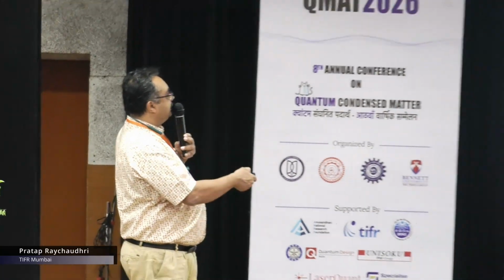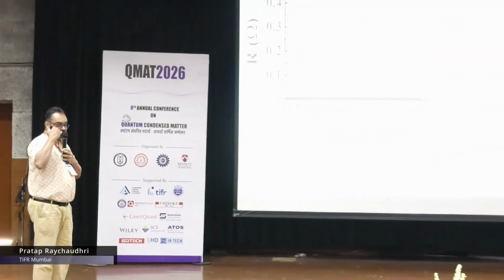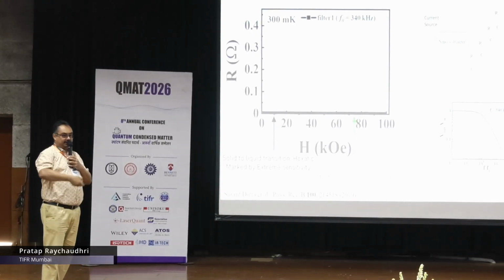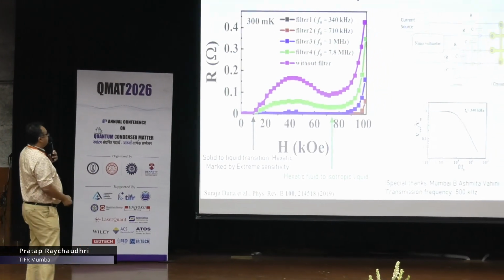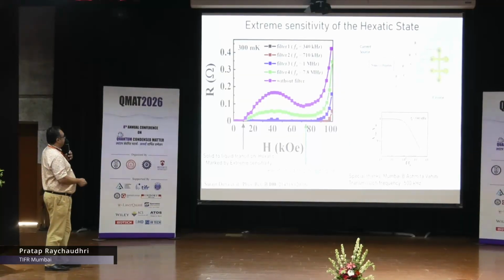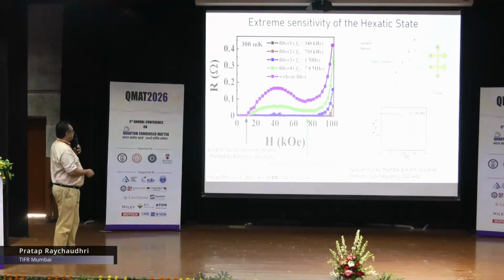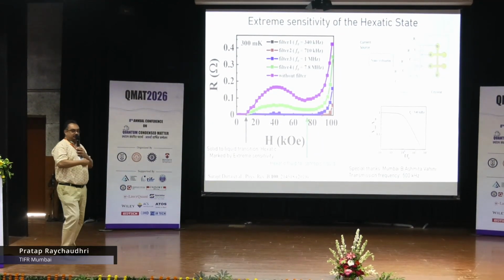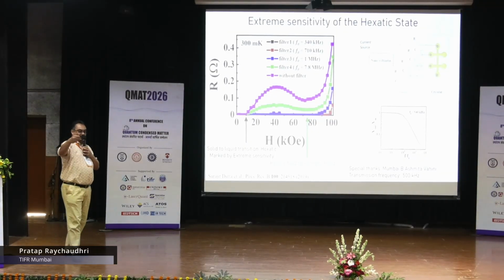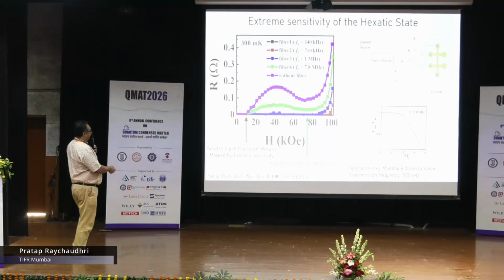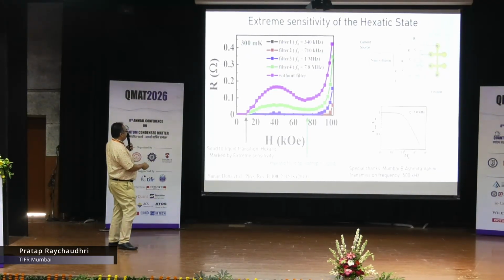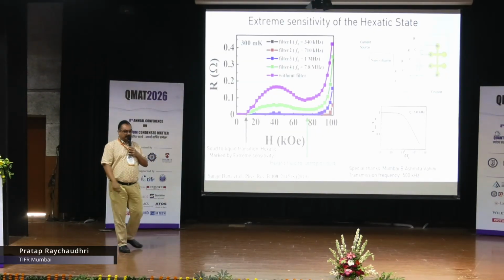If I start relaxing the corner frequency of this filter and start letting external stray electromagnetic radiation leak in, we can see immediately there is a big difference between the solid and the liquid state. In the solid state, nothing much happens. A small amount of electromagnetic radiation which starts shaking the vortices doesn't do anything. But in the liquid state, the resistance increases rapidly, and from this difference you can find out the phase boundaries, the solid to hexatic, and here this increase corresponds to the hexatic to the isotropic liquid.